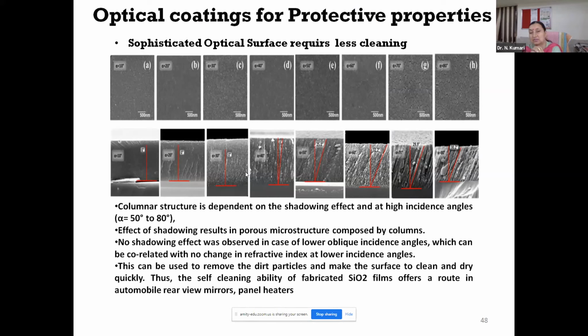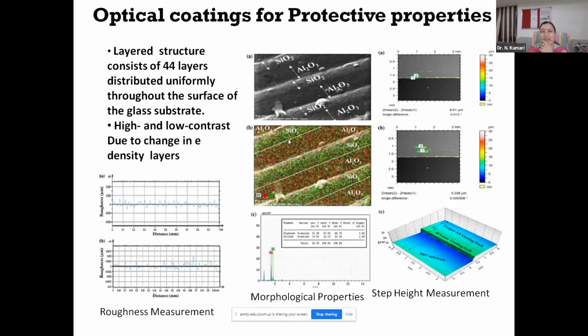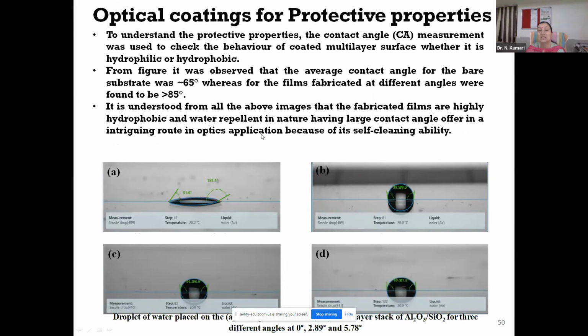So recently we did some work in that area, and we developed an optical structure where we utilized a particular coating process called glancing angle coating process to develop porous structures. These porous structures modify the surface, and they will not allow dirt or water or moisture to stick on the surface. We have done a thorough analysis of those types of coatings, and we have seen that they can be effectively used for hydrophobic or anti-dust coatings.